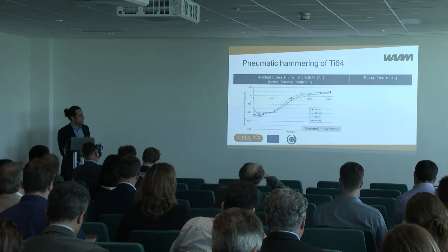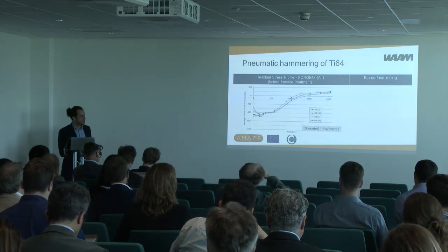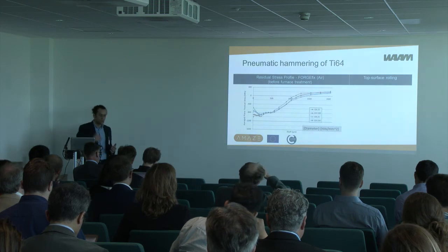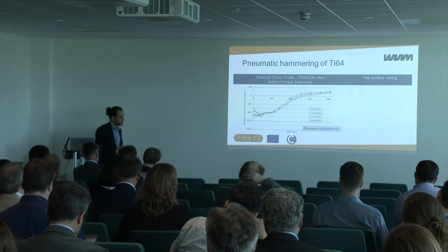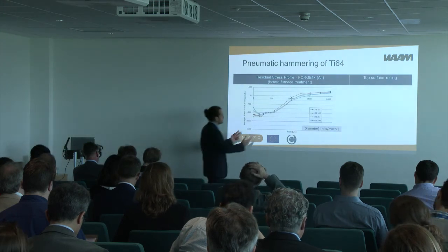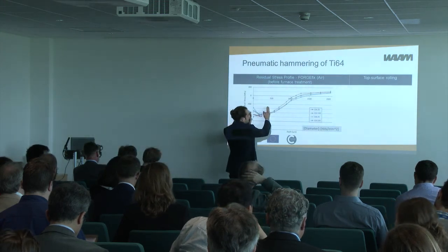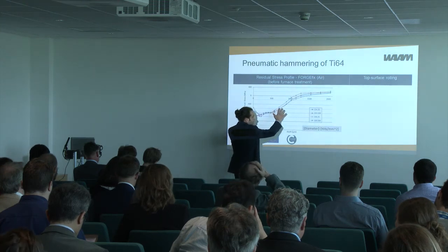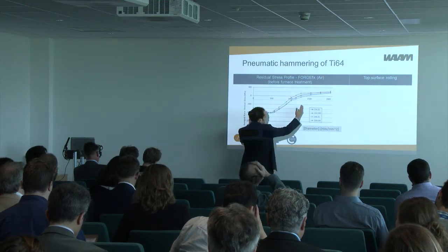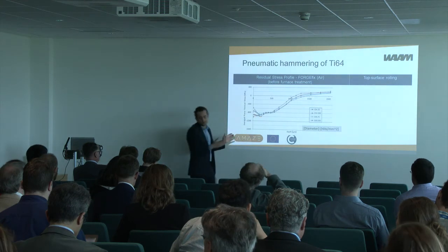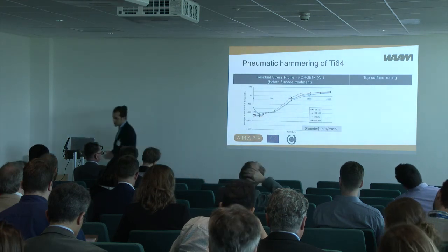So this is very encouraging in terms of applicability of this process. Nevertheless, we shouldn't forget that when we do a rolling pass, there will be another layer deposited on top. And so what is really key is that the depth of what we remelt has to be smaller than the depth of what we cold work. Because if we remelt all of this part, all of this goodness will go away. And that's what we're trying to understand now.